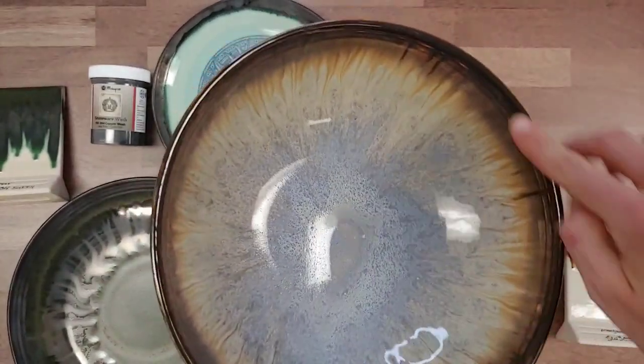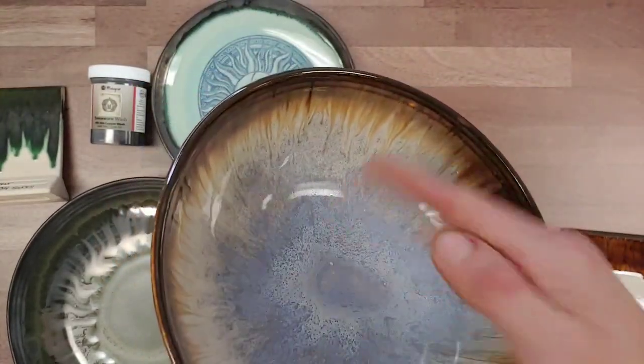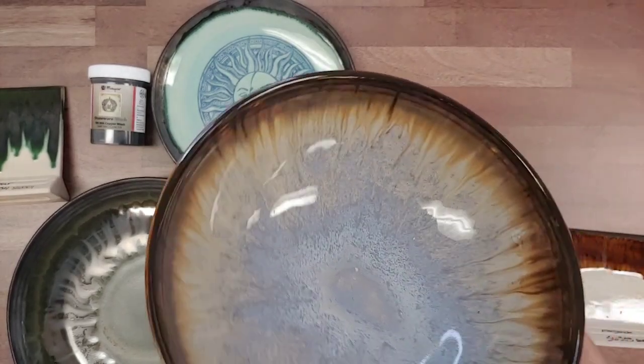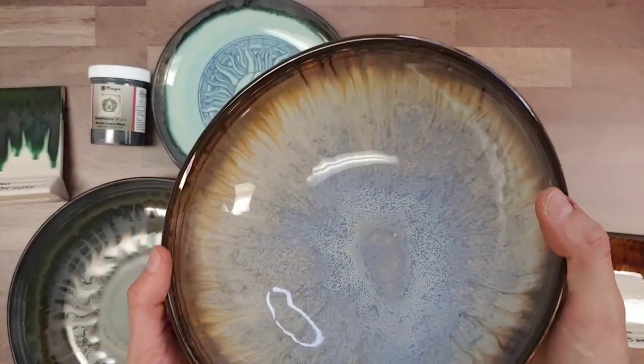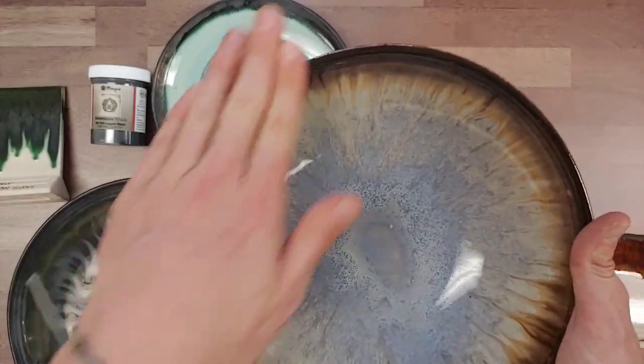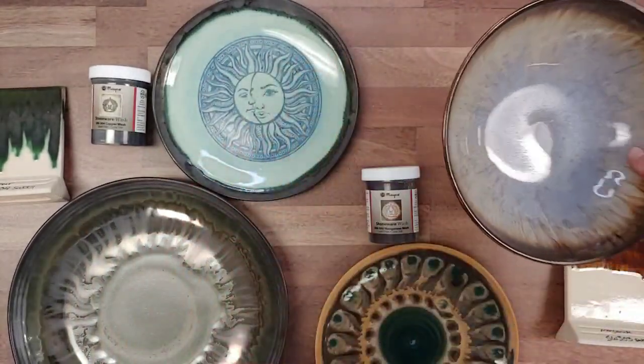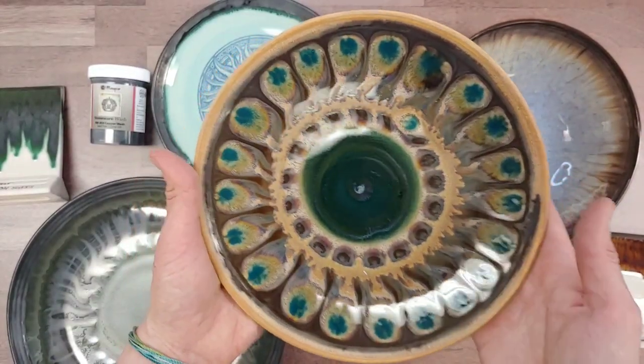Here are a couple of samples — this one has gray opal and honeycomb with the manganese wash on the rim, applied underneath all the glazes. I knew these glazes would influence mobility, so having four coats of glaze on top creates more movement, which I was really seeking out. I love how it blends right down into the glaze combination. This would be considered dinnerware safe because the manganese wash is completely underneath a sealed, dinnerware safe finish.